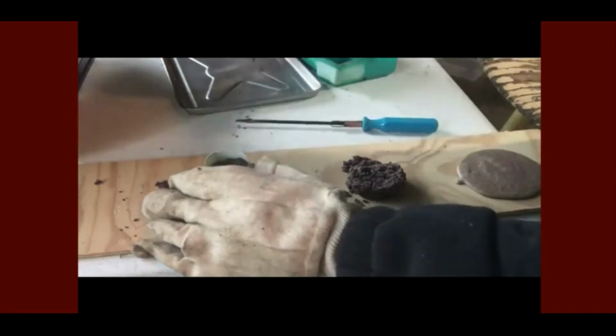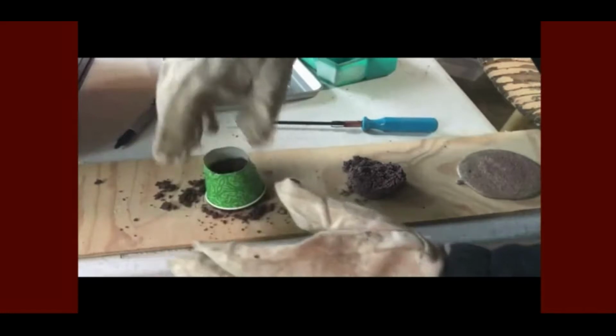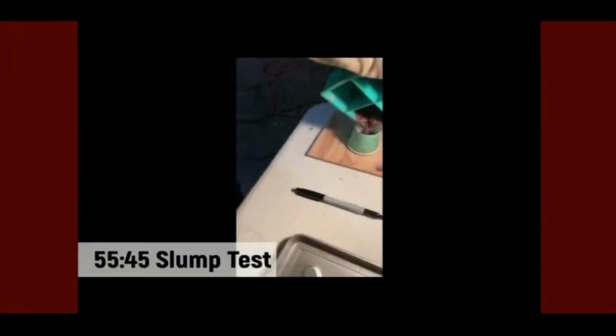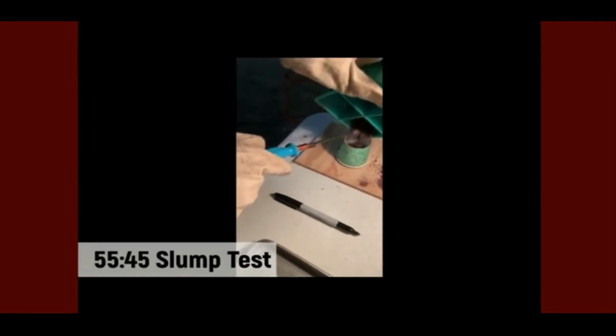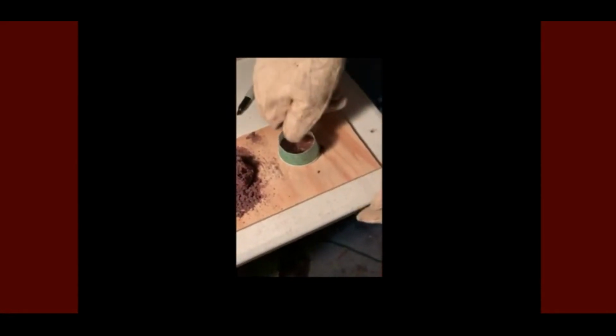There's actually a very delicate balance between extrudability, being able to actually be forced out of a system, and buildability, the ability to layer. So that's a really delicate balance and really important, which is why I did this testing. So you can see that's an even steeper ratio, really crumbly. So here is a 55-45 ratio, which was in between collapsed and zero slump. And as you can see here, it drops a little bit, but not all the way, which is called true slump, meaning that this is the optimal ratio for 3D printing sulfur concrete.